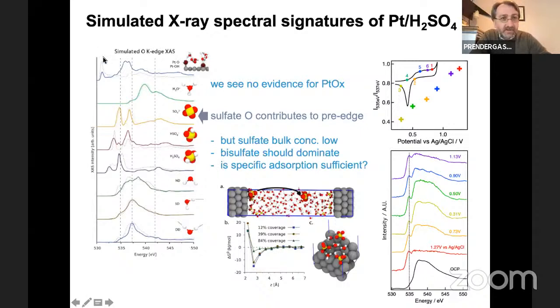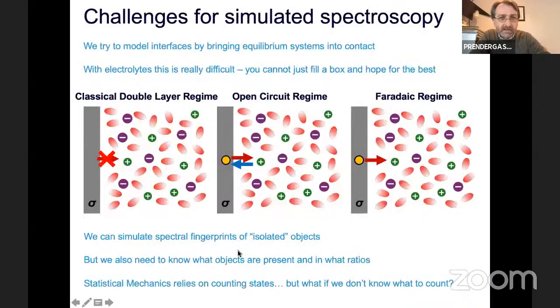One other side note, we don't see any oxidation of the surface that would produce a pre-edge peak at lower energy, and there's no evidence for that in the experiment. So, okay, those are the conditions. So this is the puzzle we're left with. And I'll take a brief aside just to talk about the challenges for simulating this kind of spectroscopy.